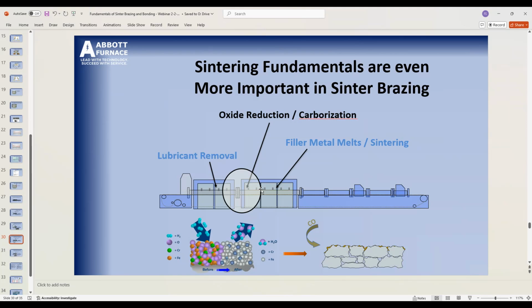And then, like I say, we have to reduce the oxides, but then we're going to come back in at 1010 C or 1850 Fahrenheit, and we're going to inject some gas in this location that has CO in it to help us to contaminate or dirty up those pores just a little bit, not enough to deter the sintering, but just a little bit to deter the capillary from stealing all of the filler metal from the gap.